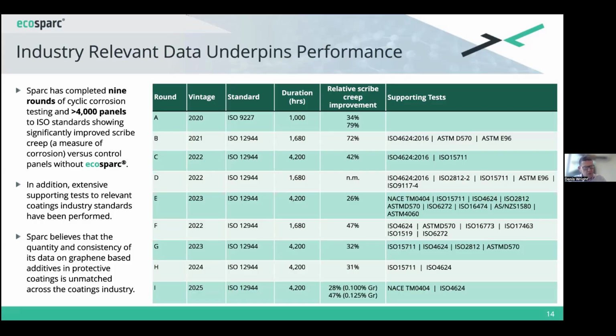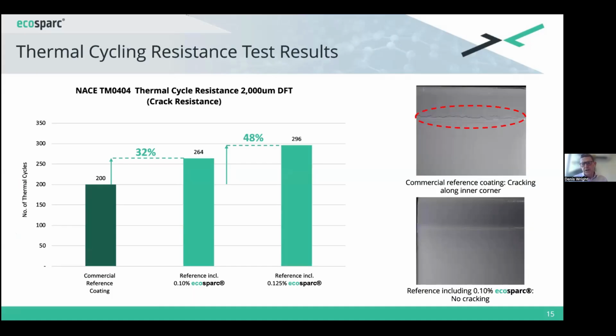Interestingly, if you look at round number I there, we've got a 28 and a 47% improvement. That was based on a commercially made coating. And if we look at that, that also correlates out into this crack testing. So we had an improvement in the scribe creep. So that's great. So we said, righto, what's going on here? And we proposed, as we have for a number of years, that there is a reinforcement of the film via shock absorption or stress absorption by the polymer. So to test that, we've done 2 rounds of crack testing, 100 test pieces each, one in triplicate.